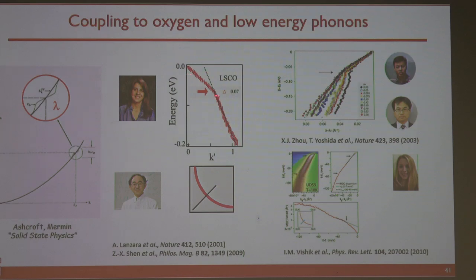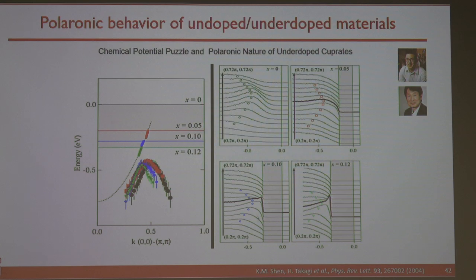Okay. And you can clearly see that basically, when you have electrons coupled to phonons, you see a sudden change in the electron's velocity at the phonon frequency. Remember that the slope is the velocity of electrons, and you can see a sudden change of slope. So this we've done. So there is pretty strong electron phonon interaction in this system. I should also say this is more technical, but this is the thesis work of Zhi-Xun Shen, and he was able to explain the line shape.